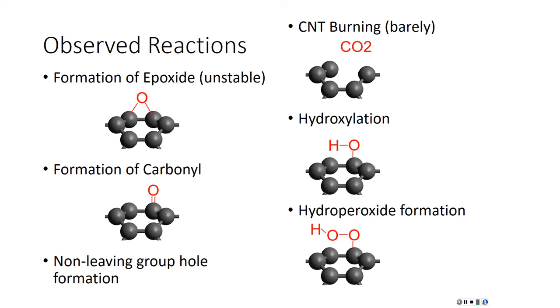So what we did see was reactions that I didn't expect. First off was the hole with no leaving group. We saw an epoxide form, and it was stable for hundreds of femtoseconds, but ultimately it did go to form a carbonyl. We kind of saw maybe a little bit of the burning with the cationic state, but not really anything like I had expected. And then hydroxylation and hydroperoxide formation that I didn't originally expect, but we saw those as well.